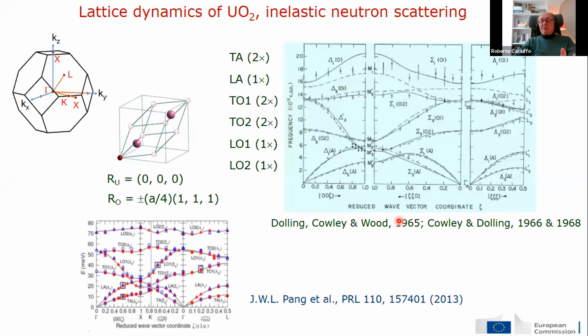Here, experiments are performed with an energy resolution of the order of the milli-electron volt. And experiments, of course, have been done. For instance, the lattice dynamics of UO2 was extensively investigated by inelastic neutron scattering already in the mid-60s. These curves are the dispersion curves for UO2.